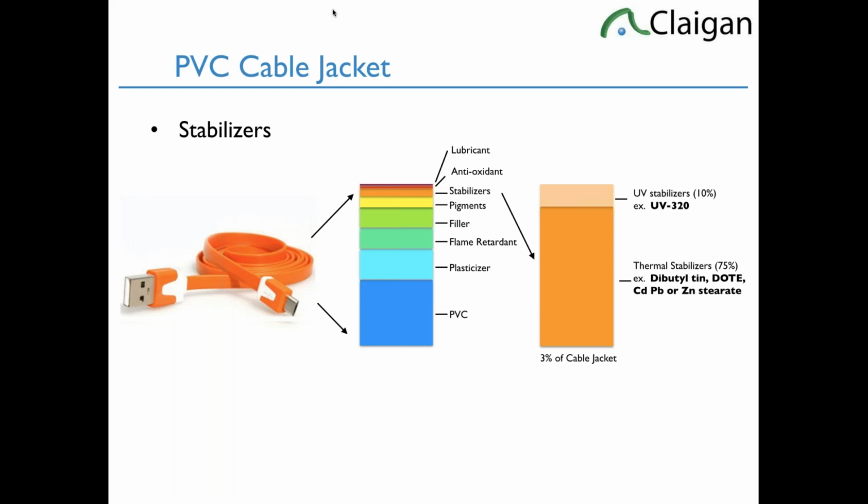We're more likely to see those particular benzotriazoles, UV-320 and such, in EPDM, outdoor rated EPDM or coax, but we can see it in PVC. It's rare, but if it is there, it's well over 1,000 ppm. So the stabilizer itself often contributes heavily to the potential of non-compliance with a cadmium or lead or organotins or, infrequently, the UV-320s, etc.